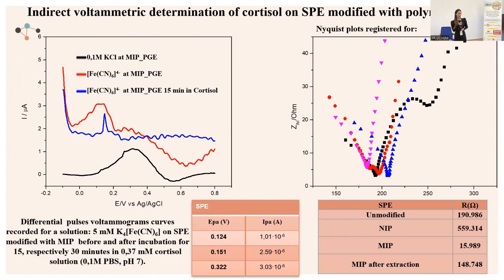In order to have a comparison, similar studies were done on screen printed electrodes, and from differential pulse voltammograms it can be observed that no modification took place in the case of these electrodes. And in the final, for the purpose of checking if there were some problems with the electron transfer at the surface of the electrode, electrochemical impedance spectroscopy was realized using the ferrocyanide as the redox couple.